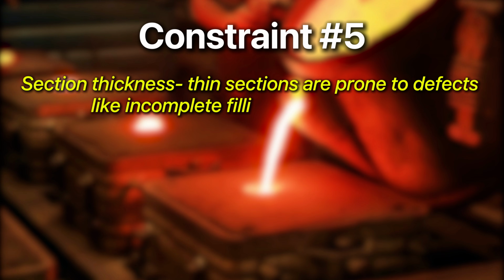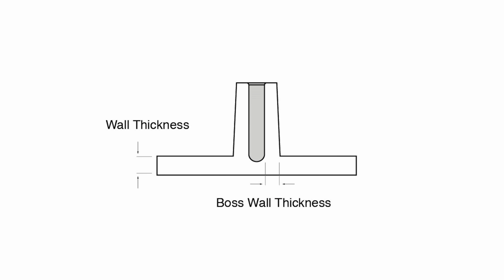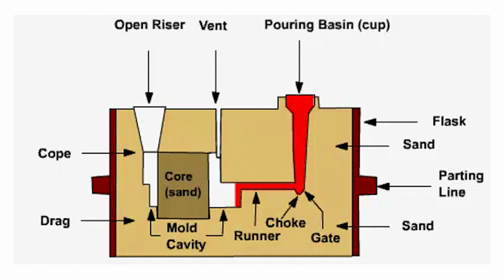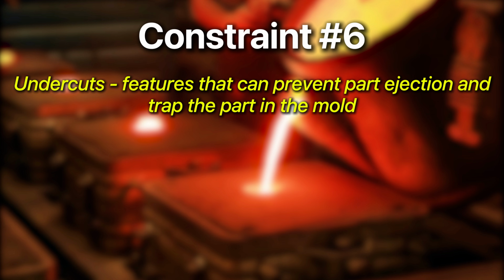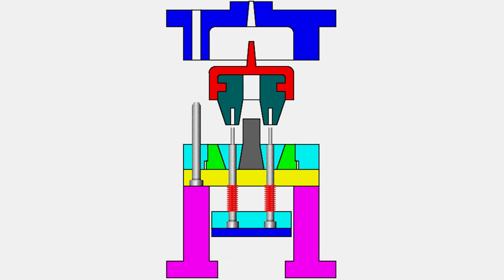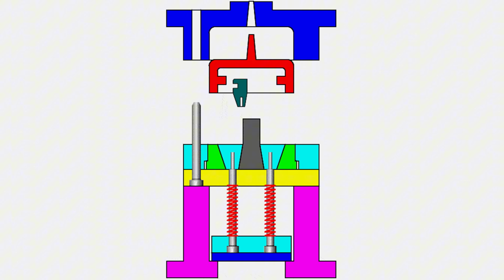Thin sections are prone to defects like incomplete filling or rapid cooling, so avoid walls thinner than 3 millimeters for metals. Thicker sections will require risers to feed material during shrinkage. Sixth is undercuts. Similar to CNC machining and injection molding, casting can struggle with undercuts, as these can trap the part in the mold. Minimize or eliminate undercuts, or design the mold to include cores to manage complex internal geometries.